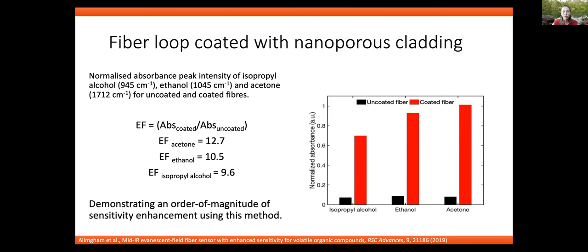However, if we were to functionalize the nanoporous silica with a hydrophobic coating, then we would expect that this enhancement will be lower for polar groups and perhaps better for some others. And this is what will allow us to tune the coating for specific applications.